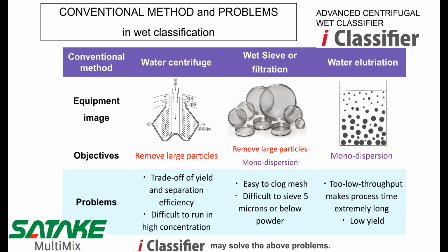There are many problems in conventional wet classification methods. Water centrifuge has a trade-off of yield and separation efficiency. Also, it is difficult to run in high concentration. Wet sieve or filtration is easily clogged in the mesh openings. Also, it is difficult to sieve powder of 5 microns or below. Water elutriation has too low throughput, which makes processing time extremely long, and the yield is low. These systems cannot fully utilize the wet system advantage, which is that disintegration is easy with liquid.